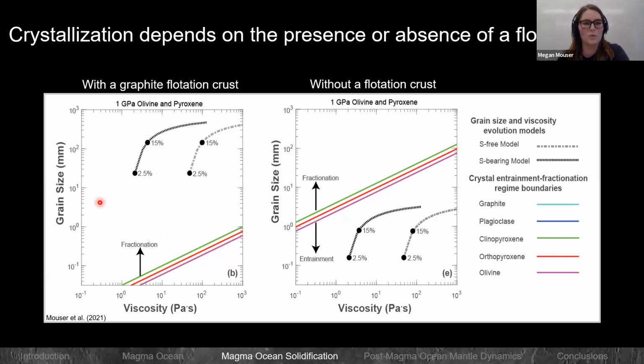So over here, we have the scenario with a graphite flotation crust on the left side, and on the right side, we have the scenario without a flotation crust. So this is just a snapshot at 1 GPa in the mantle, looking at what happens with olivine and the pyroxenes. So these colored lines here are the critical grain size boundary. So above these lines, you have grain sizes that are large enough and the density difference is great enough that they can fractionate from the liquid. Below this line, you have small grain sizes and they will remain entrained. So that's what these colored lines are.